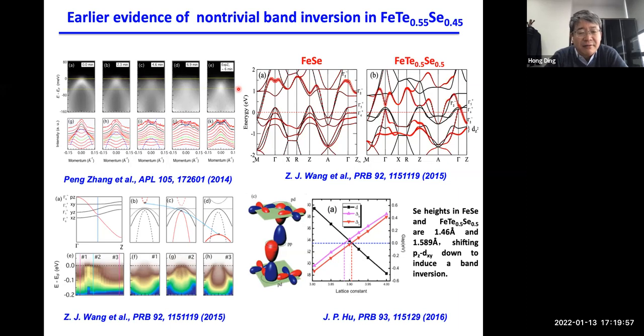So our group at that time was also doing topological metals, so we are very sensitive to the iron Dirac cone structure, and we were also doing the iron-based superconductor, especially iron selenium doped by potassium, which showed that there is an electron band with the orbital character of the PZ band. So we kind of suspected that the PZ band can come down. If it comes down, it may cross these D orbitals, D bands.